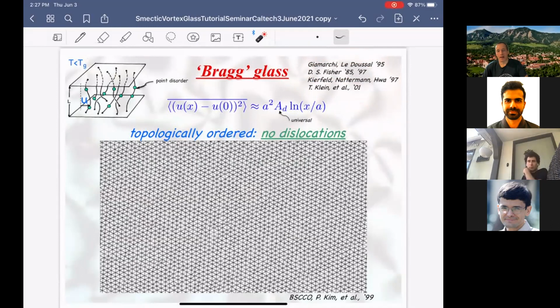One cool property of Bragg glass, well, there are 2 points of view. One can say, well, there's this question of principle, does Bragg glass exist or not? But alternatively, one can think about it even if Bragg glass does not exist as a distinct phase from a vortex glass, and there's a finite Larkin scale, a finite dislocation length scale, which is not infinite. If you have such a situation, that means dislocations beyond this length scale unbind. However, one can always look at smaller system sizes and study the system on the smaller scales. And when one does that, one discovers that, in fact,